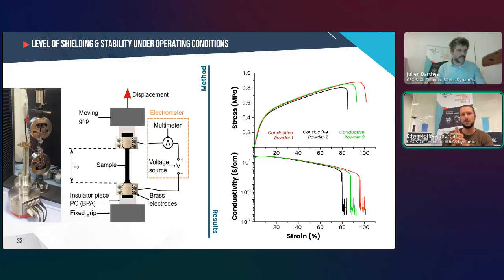The red curve associated with conductive powder 1 demonstrates the best balance between elongation at break and preservation of the conductivity. This indicates that the percolation network remains connected even under large deformation, while the other formulations lost conductivity earlier. Overall, this experiment confirms that our selected silicone-filler pair maintains its conductive network under strain, meaning our materials can retain their shielding efficiency under real operating conditions as required for flexible seals in aeronautic and defense applications.